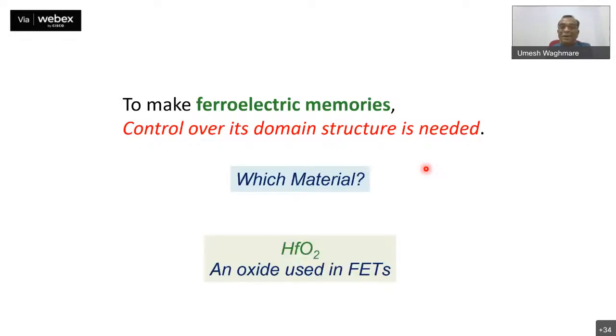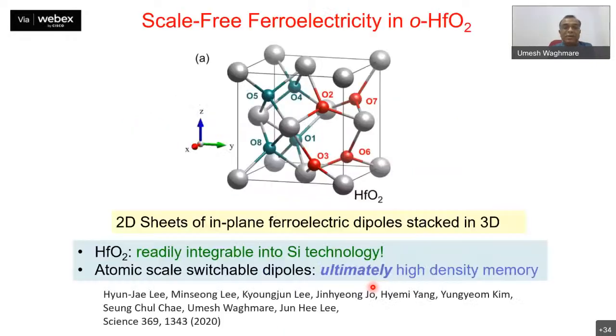That's where we stumbled upon hafnium oxide, which is an oxide already used in field effect transistors as a dielectric material. But if hafnium oxide is grown in a specific crystal form called the orthorhombic crystal structure, it is ferroelectric with very exotic ferroelectricity. Unlike barium titanate, here the ferroelectricity is driven by oxygen atoms, not hafnium. Okay, so it is readily integrated into silicon. And what we will show is that it has ultimately high density memory.